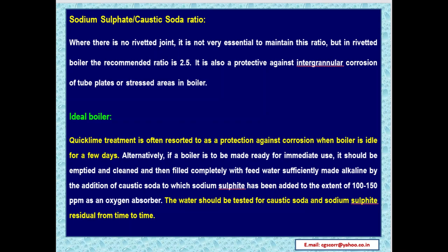Idle boiler. Quick lime treatment is often resorted to as a protection against corrosion when a boiler is idle for a few days. Alternatively, if a boiler is to be made ready for immediate use, it should be emptied and cleaned and then filled completely with feed water, sufficiently made alkaline by addition of caustic soda, to which sodium sulphite has been added to the extent of 100 to 150 ppm as an oxygen absorber. The water should be tested for caustic soda and sodium sulphite residual from time to time.